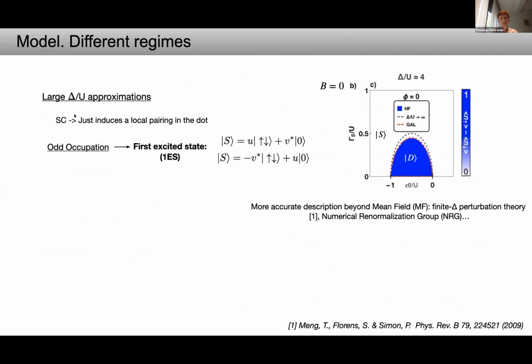In this regime, the superconductor just induces superconducting correlations in the dot in such a way that if we start in an odd occupied Coulomb diamond, the first excited state will be singlets formed by combinations of states with even occupation. So, phase diagram: energy of the dot versus gamma S, coupled to the superconductor, looks like this. We clearly see a doublet dome, which is surrounded by a singlet phase.